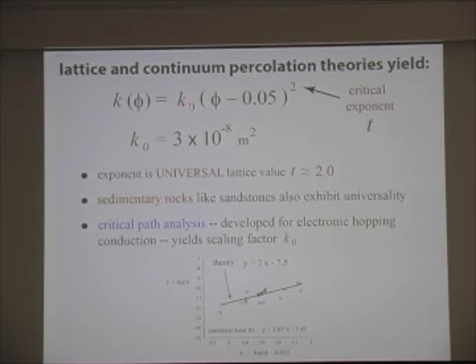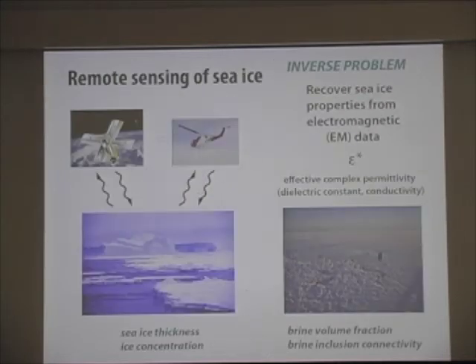And then also this constant in front, we actually compute that. It's not just a fudge factor that we stick in to fit the data, it's something that we compute from our X-ray tomography data. And we use a theory called critical path analysis, which is another example of cross-pollination, originally developed for electronic hopping conduction in doped semiconductors, like the kind of semiconductors that are in your computers. And we take that and, again, apply it to sea ice. And so here's a nice comparison between our theoretical predictions. There's a theoretical prediction, and then here's the statistical best fit of this data. And we have a lot of other types of theories like this that do quite well.